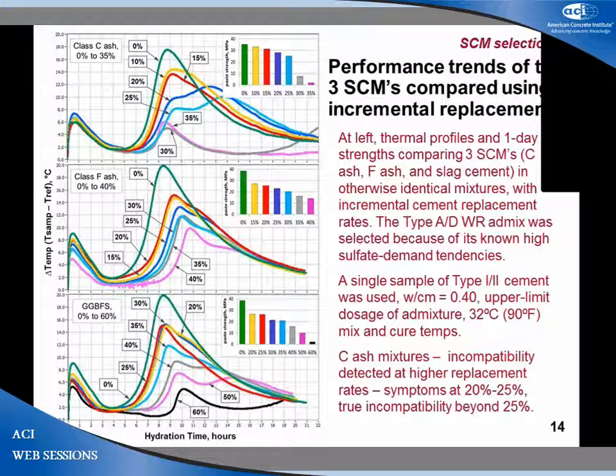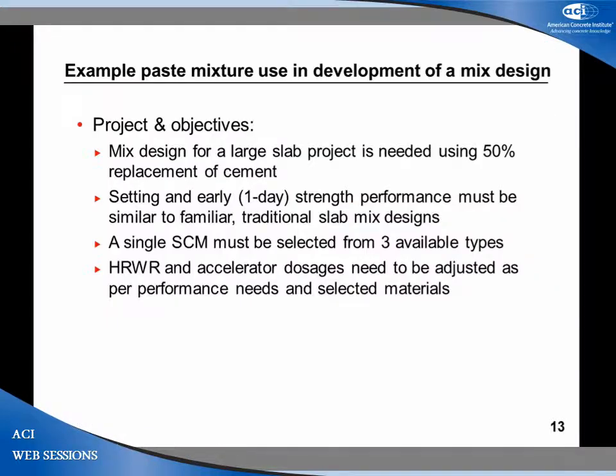And for those with experience in reading thermal profiles, that's an indication of some problematic potential. And then the strengths are an indication, as we see here, that misbehavior, incompatibility is going to be a potential issue in the C ash. But go back to the objectives. What we really want to do is try to develop this mix design. Now that we know there might be some issues with the C ash, that's something for us to watch in the process.